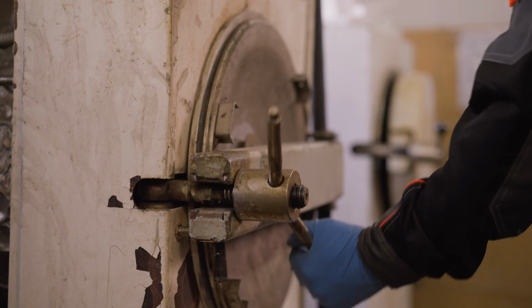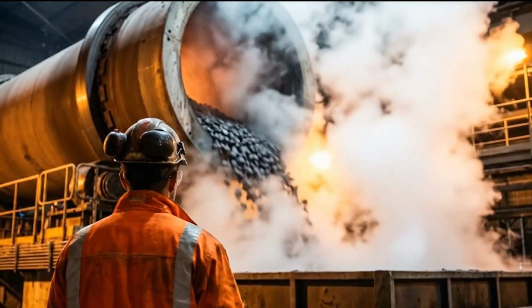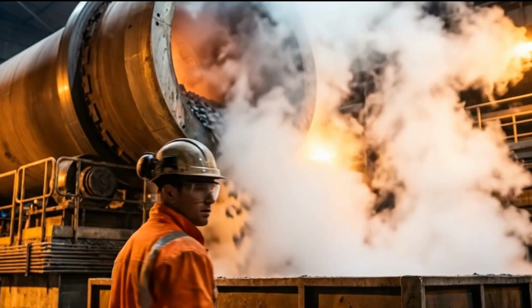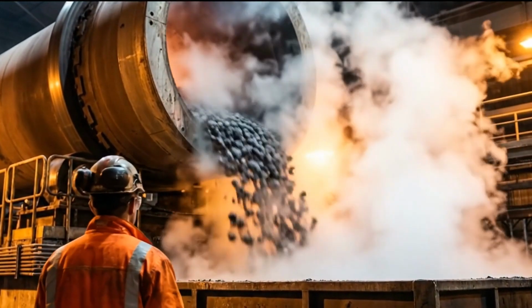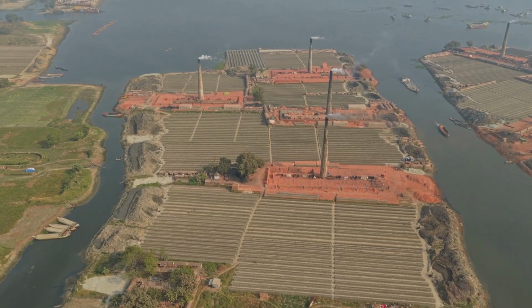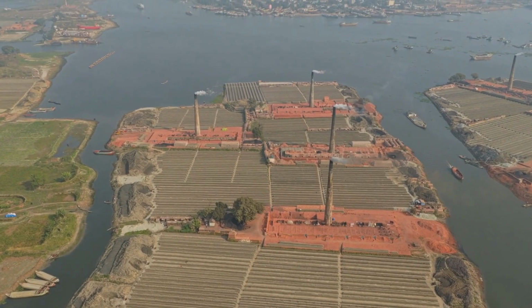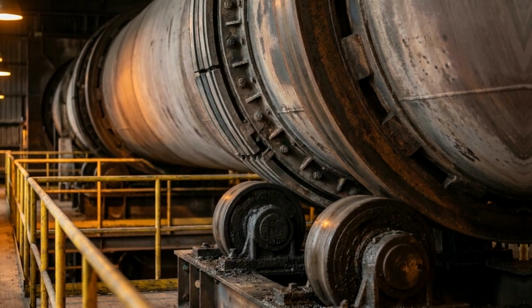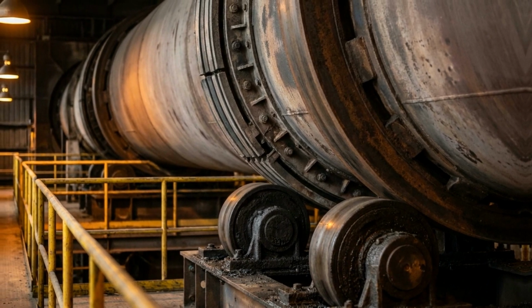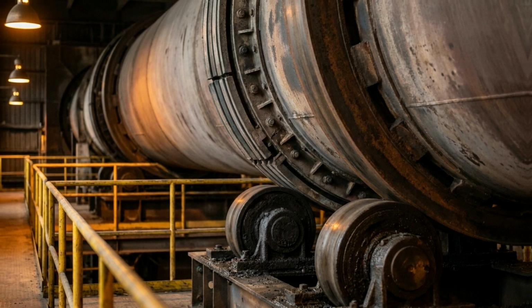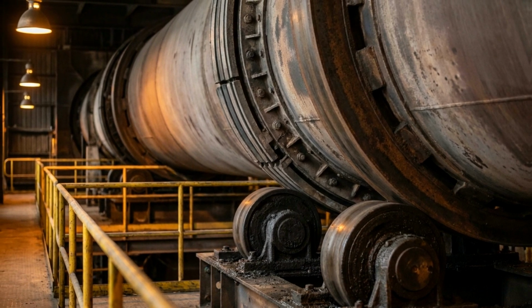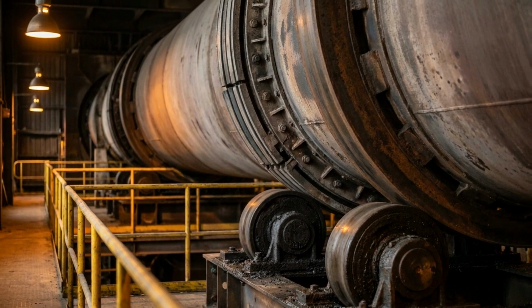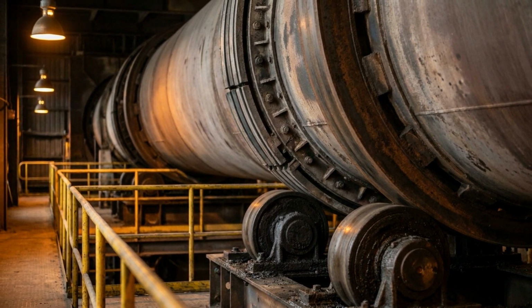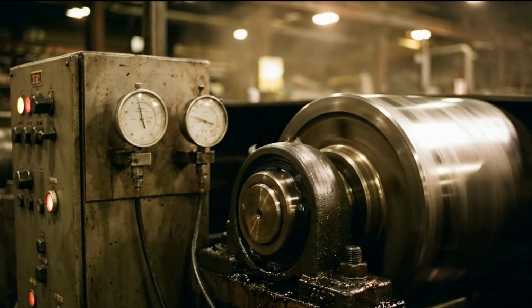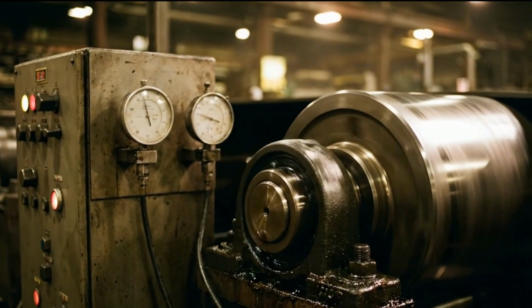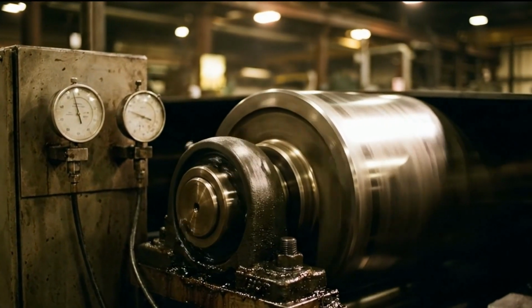The kiln doesn't stop to unload. Clinker falls out of the lower end continuously, drops onto a grate cooler where high-pressure air quenches it rapidly, and moves off to storage. The kiln keeps turning. The engineering challenge that defines kiln operation is thermal expansion. A 200-meter steel tube running at 1400 degrees internally expands significantly along its length as it heats up and contracts again when it cools. The support system, the riding rings, the rollers, the thrust mechanisms, has to accommodate that movement without allowing the tube to migrate too far in either direction.